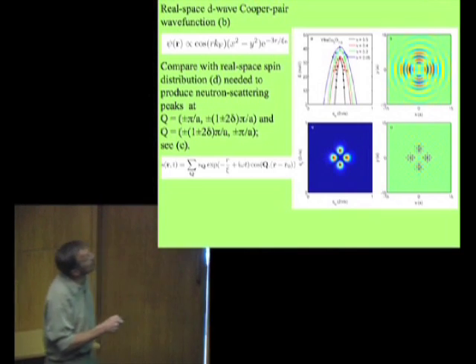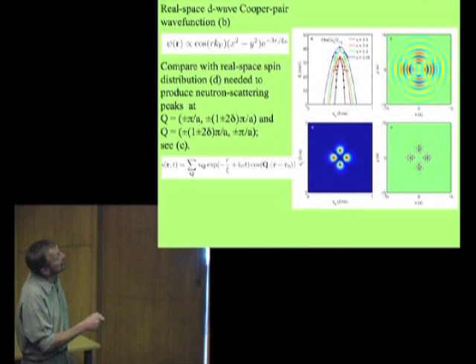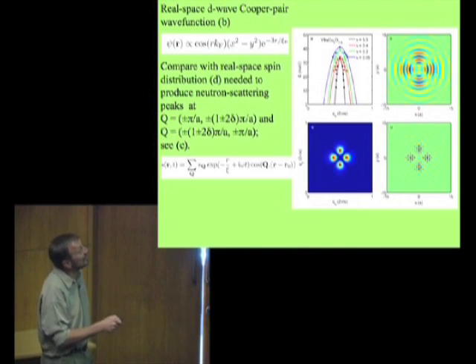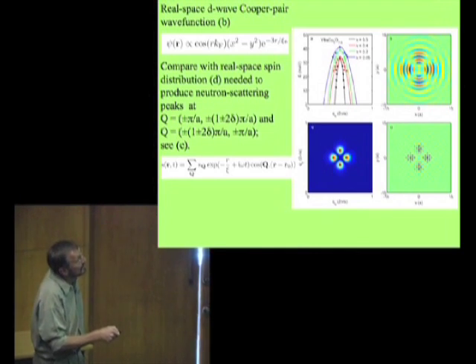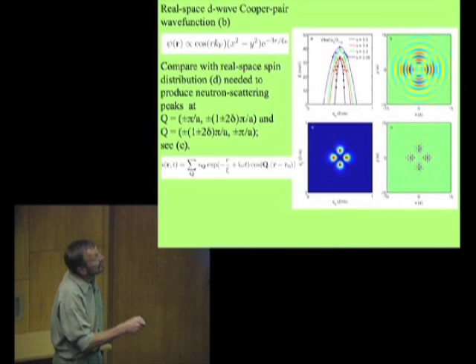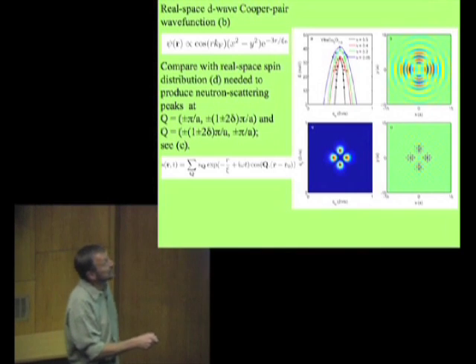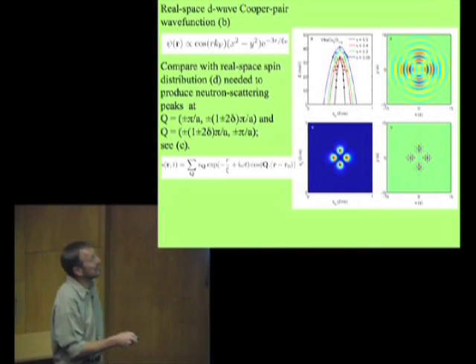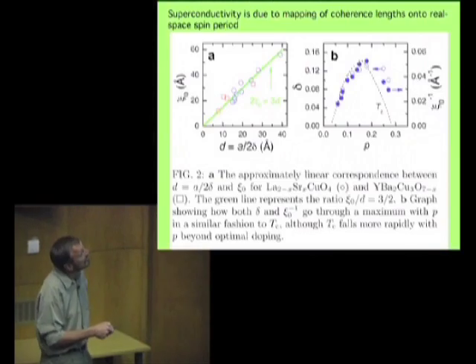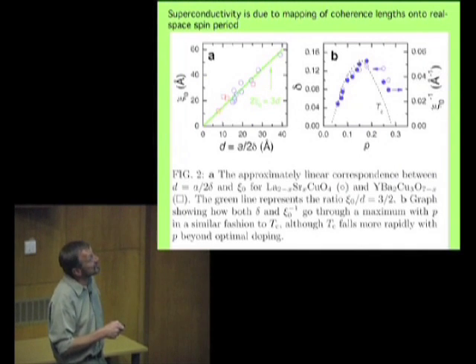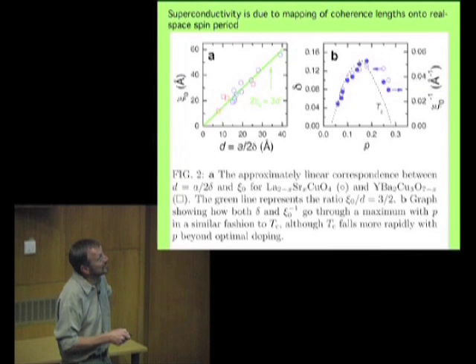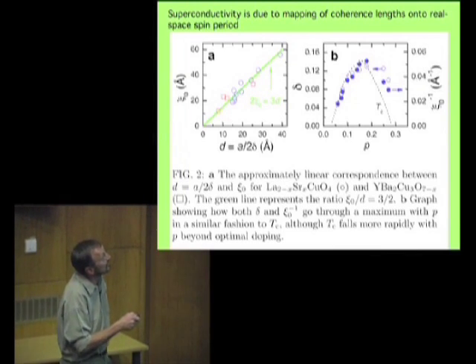The length scale of the other one is given by this parameter delta here. So by looking at the maxima in spin density and the maxima in probability density, it should be possible to see what the condition would be for matching these two things up. It turns out that the condition is that the coherence length divided by this parameter d is just 3/2. That's this green line plotted here.